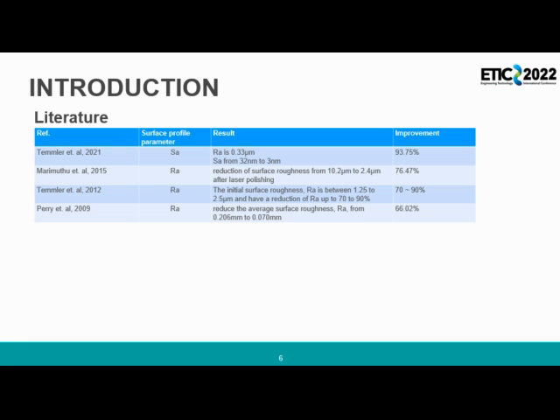In a previous study from Temmler, a laser was used to polish tool steel. The initial surface roughness Ra is 0.33 micrometer and has Sa from 32 nanometer to 3 nanometer after polishing. This sums up that laser micro polishing helps decrease the surface roughness of material and gives a better surface finish. Experimental results from Marimuthu also showed a reduction of surface roughness from 10.2 micrometer to 2.4 micrometer after laser polishing.